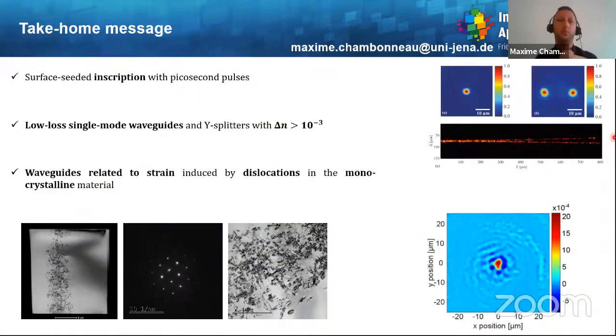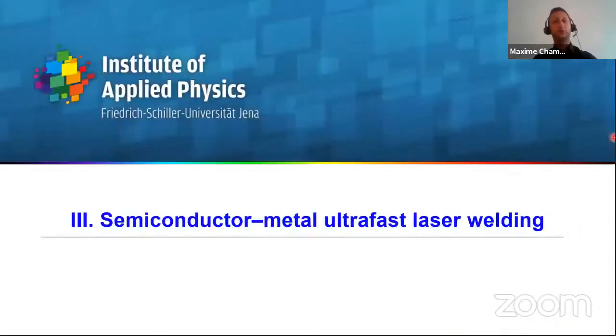So here is the take-home message for that part. With surface seeded inscription, we could write low loss single mode waveguides with picosecond pulses as well as Y splitter with a positive refractive index change higher than 10⁻³. And the written waveguides rely on strain induced by dislocations in the monocrystalline material. So now I will move to my second topic, which is semiconductor to metal ultrafast laser welding.